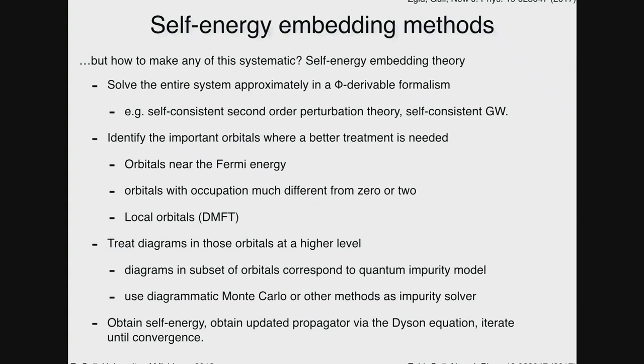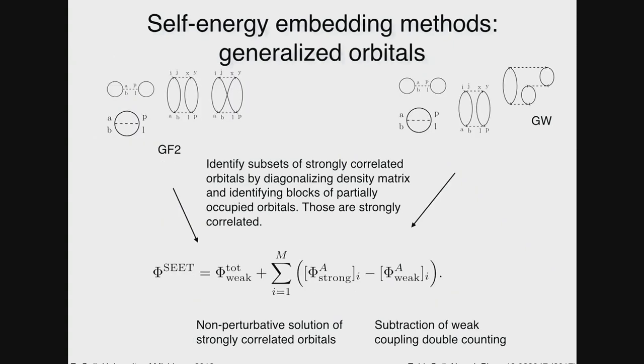So the diagrams in a subset of orbitals corresponds to a quantum impurity model. Using those diagrammatic Monte Carlo methods, you can solve these quantum impurity models non-perturbatively, and you can then insert or embed the solution of that impurity model self-consistently into a weak coupling simulation. As you make that impurity subspace larger and larger, you have a small parameter, namely the number of orbitals that you take, or one over the number of orbitals that you take, and you can obtain self-energies and propagators via the diagrammatic equation, iterate, and obtain a result. That sounds nice in principle.